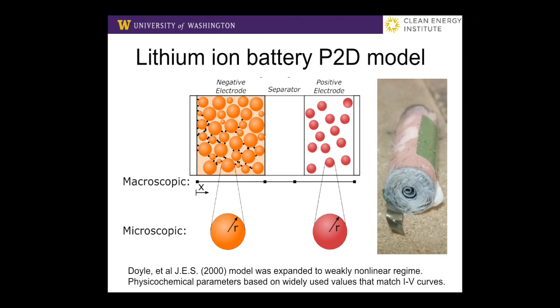The physics of the electrodes is porous electrode theory. So we have an effective porosity, we have tortuosities, transport through both of these two porous electrodes. But embedded in there, we include the physics of interparticle transport, because a lot of the low frequency stuff is getting lithium in and out of the solid state. And so we have in parameters like the size of the particles that are in the slurry.